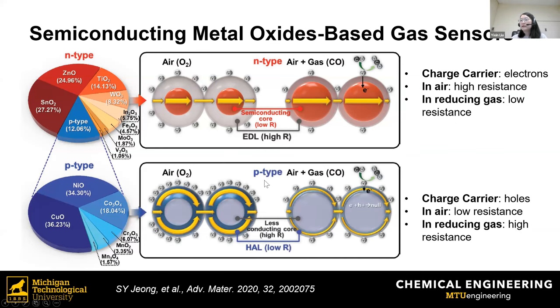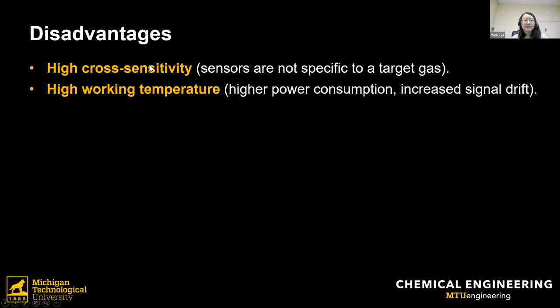The same rules apply for P-type materials, but they respond in a different direction. Up to now, from this sensing mechanism, you may think metal oxides are not particularly specific to a certain gas. It seems like anything could interact with those oxygen species and lead to a gas sensor response. And you're absolutely right. One of the drawbacks for a long time for metal oxide gas sensors is the high cross sensitivity, meaning they are not very specific to a targeted gas. Of course, different metal oxides have different catalytic activities and affinities to different gases, but it's almost impossible for a single sensor to detect just one gas. They always have some kind of cross sensitivity.